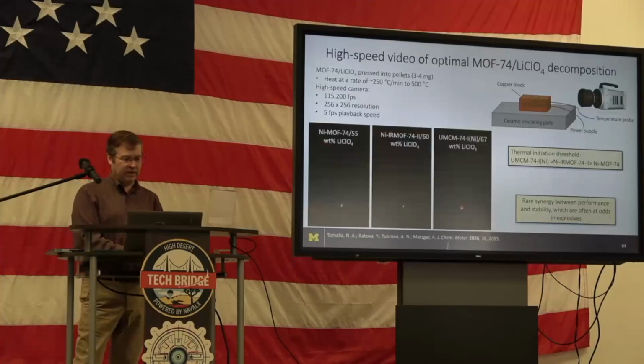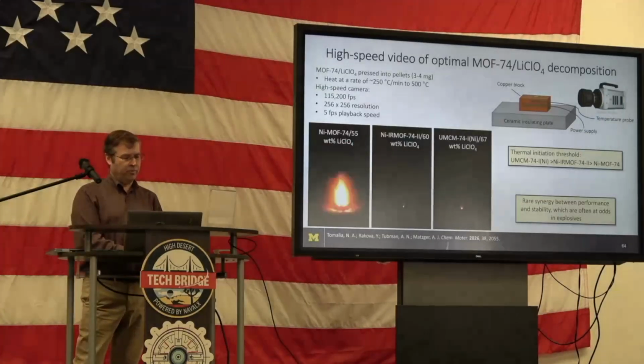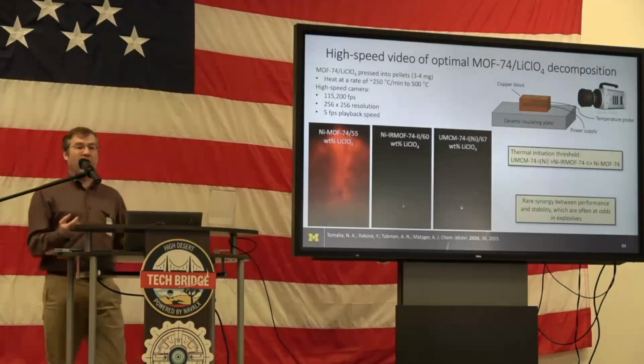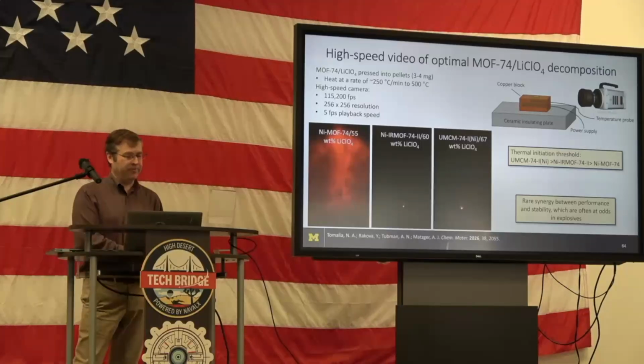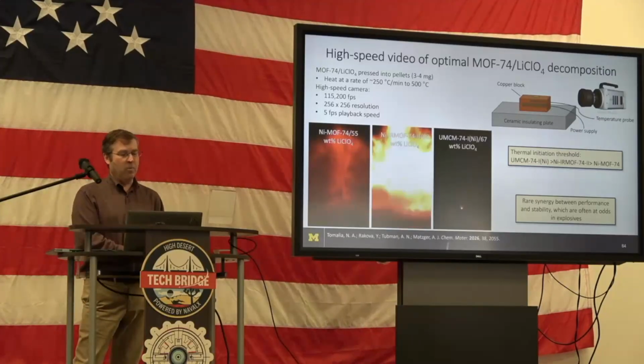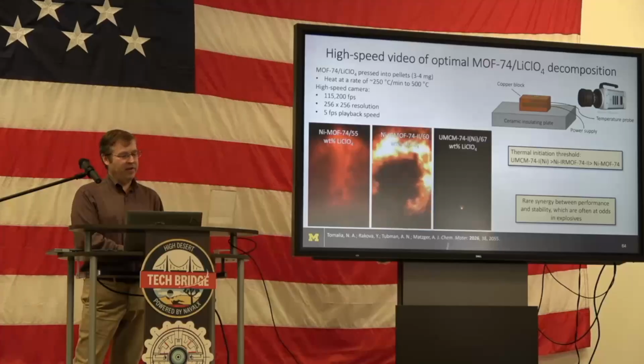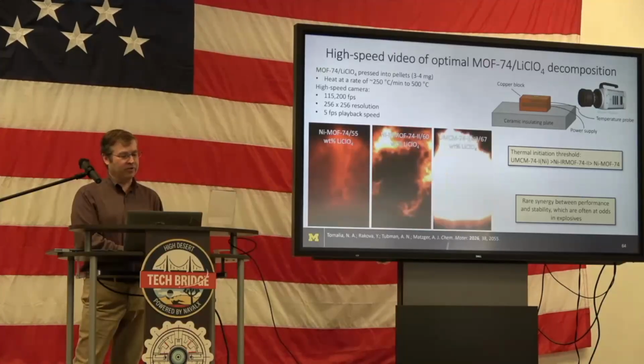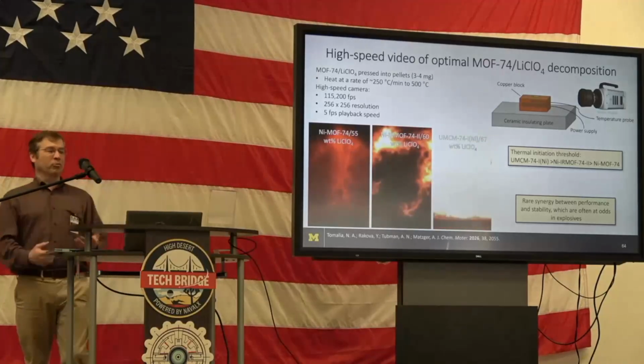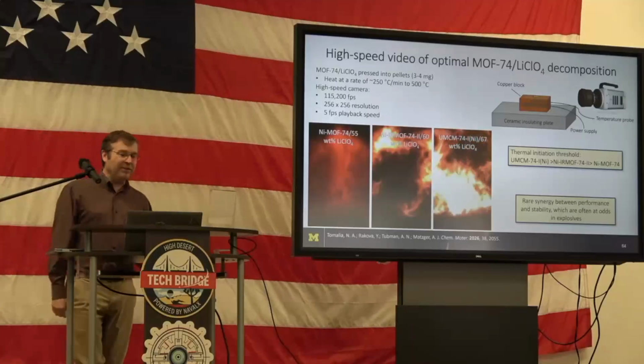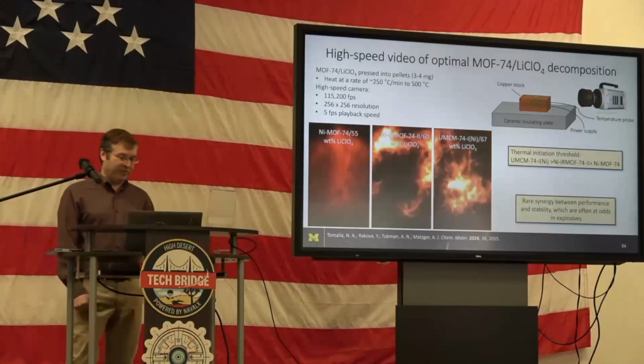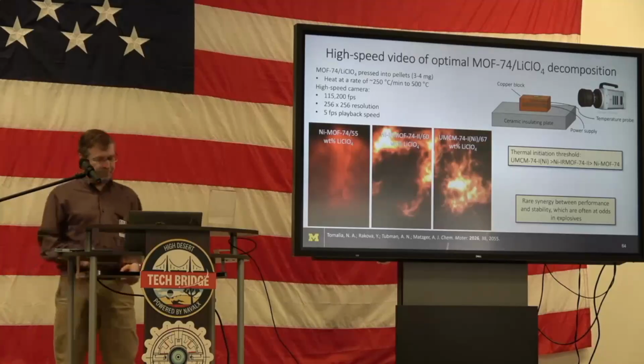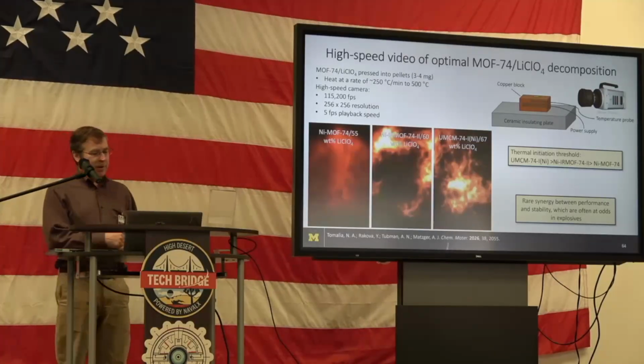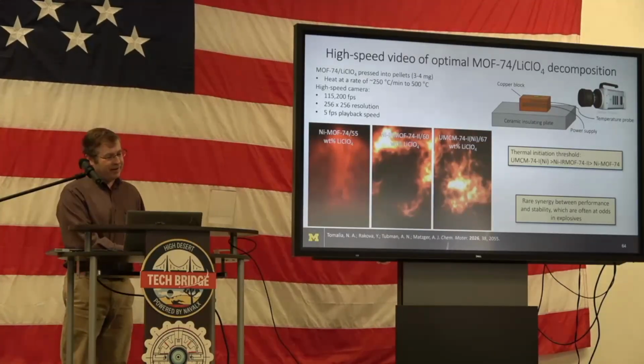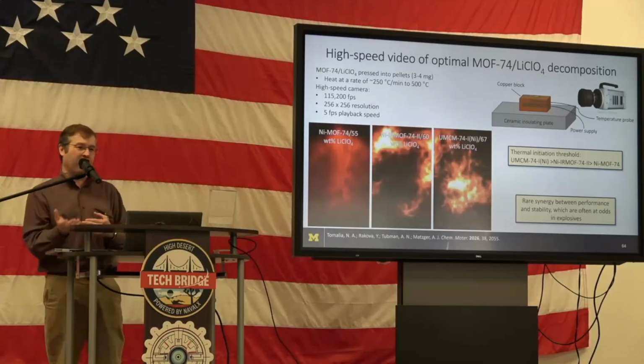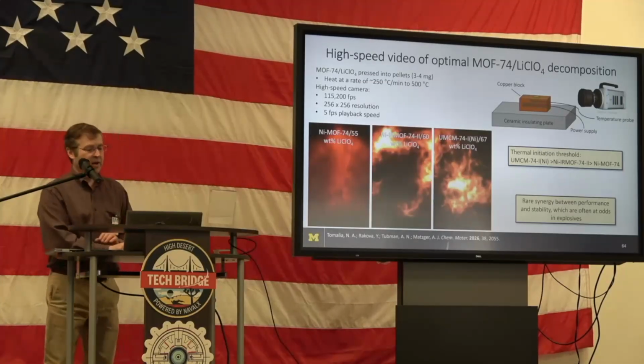Okay, but let's see if these movies will play. All right, so that's the nickel MOF74 physical mixture. Here's the now more extended, and then this is the diyne super extended one. So even visually, you can see a big difference when these things go off by high-speed video. But again, the thermal stability, you don't normally get higher performance and higher thermal stability, but here you do.